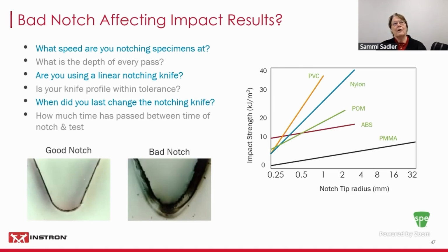I think if you do 500 notches and you look and you're still getting a really good notch, there may not be a reason to change right then, but it just goes to say you want to pay attention to how many notches you're cutting, and you want to continue to check what the notch is looking like and not assume it's a good notch. The other thing, how much time passed between the time you cut the notch and you take it over to the pendulum and run it? As we know, you're going to heat the polymer up. If you run right to the pendulum and start testing, well, it could still be warm. That can have an effect versus if you let it sit and cool and toughen back up, if you will.